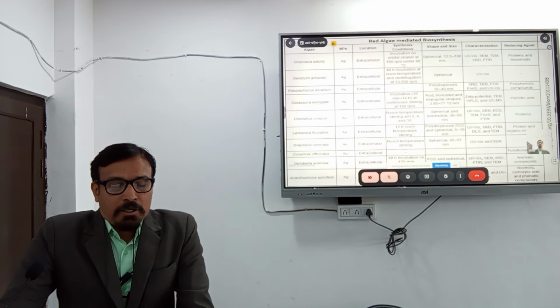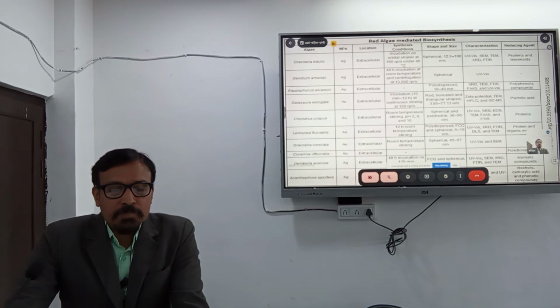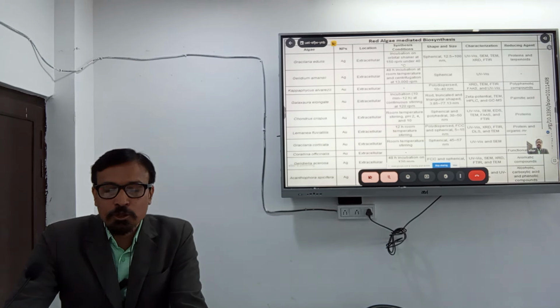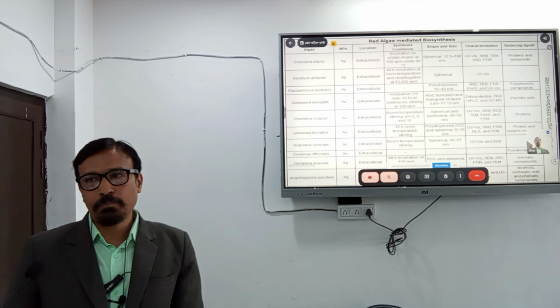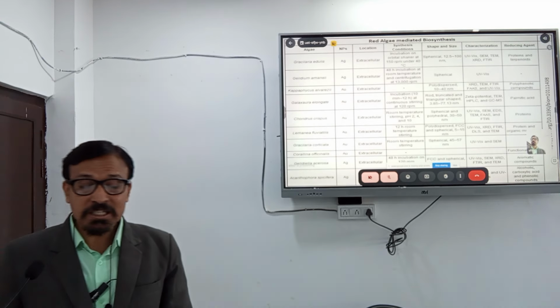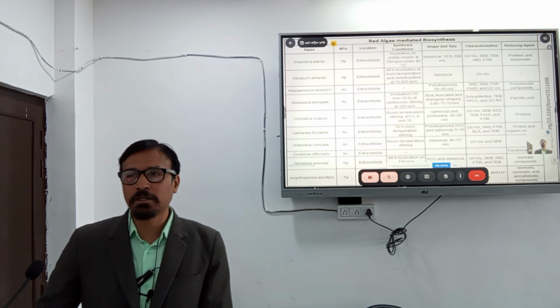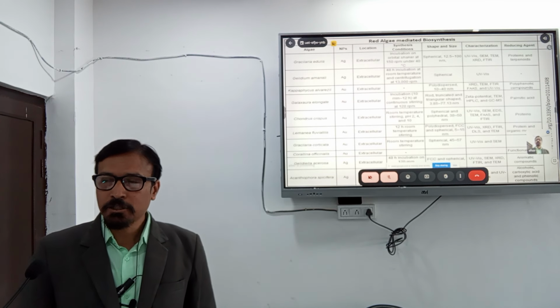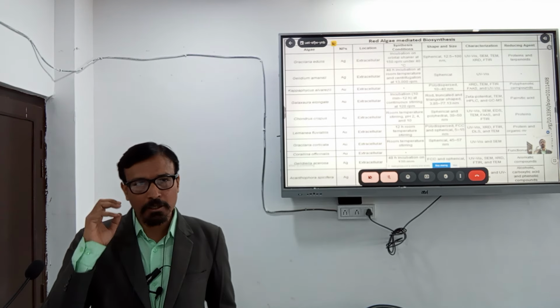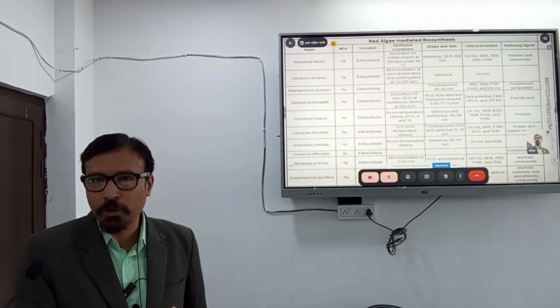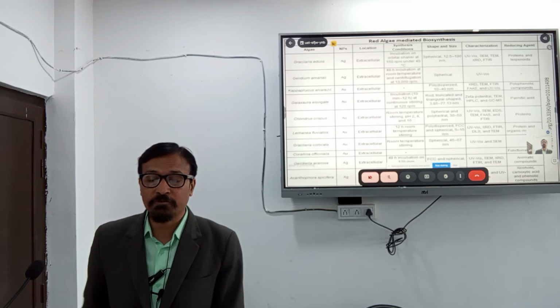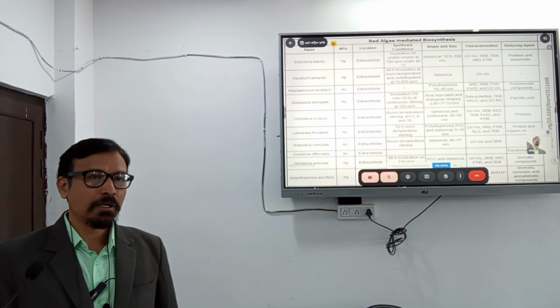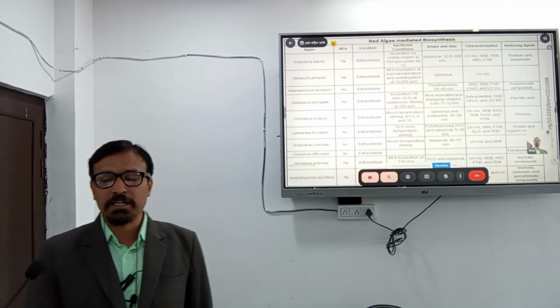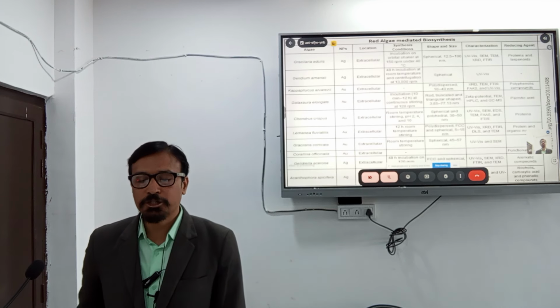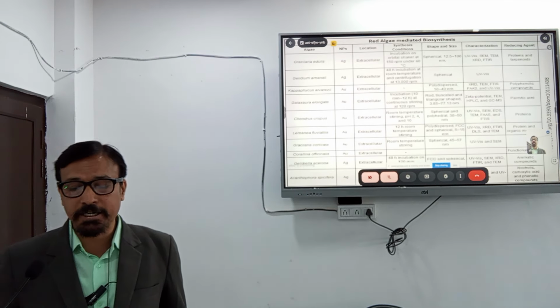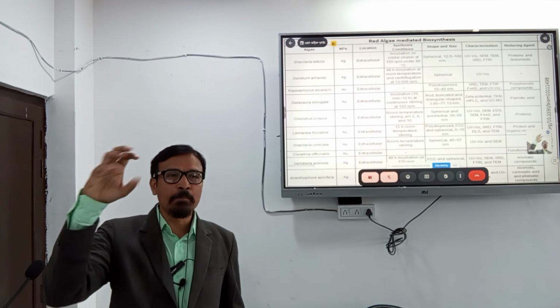Okay. So next is the Gelidiella acerosa, with which we can produce the silver nanoparticle. The location is extracellular, and 48 hours incubation at 120 RPM will be sufficient, with which we can obtain the FCC and spherical particles, and the characterization by UV vis, SEM, XRD, FTIR, TEM. So these are the aromatic compounds.